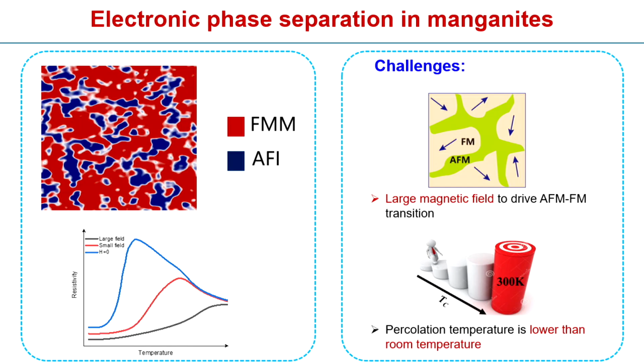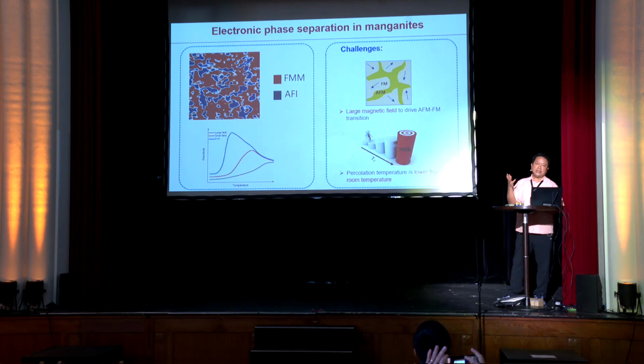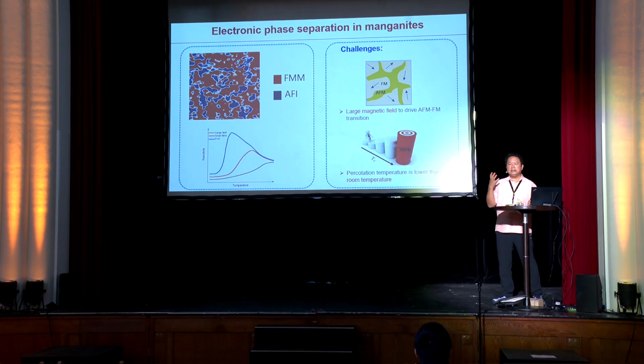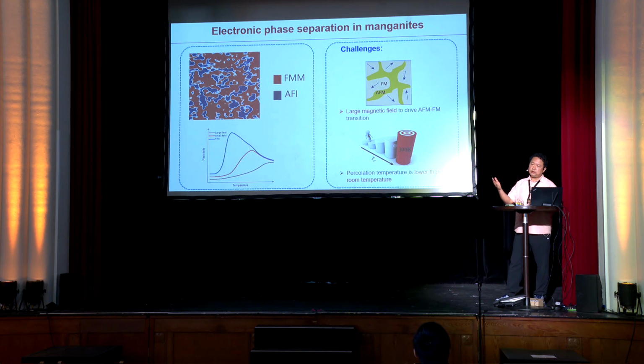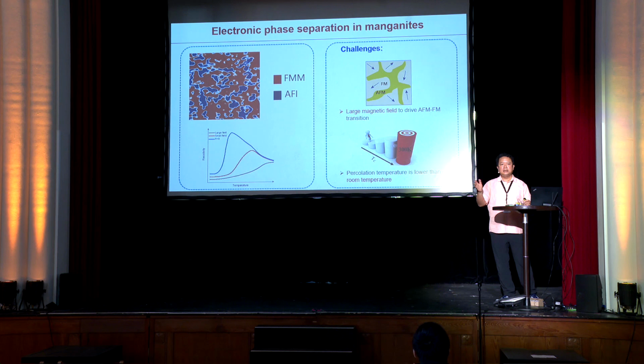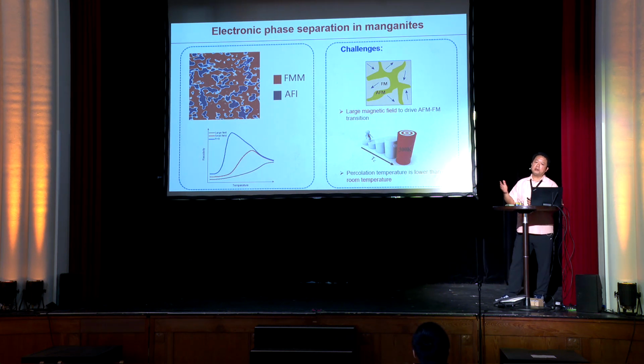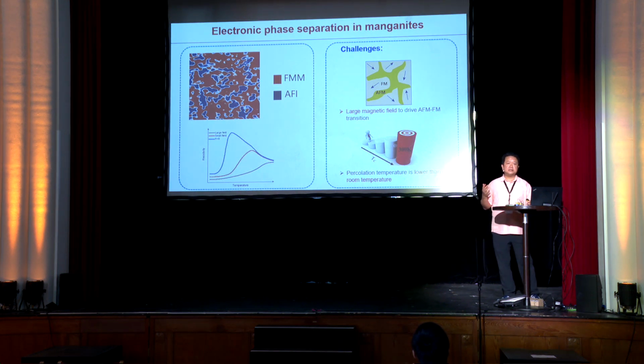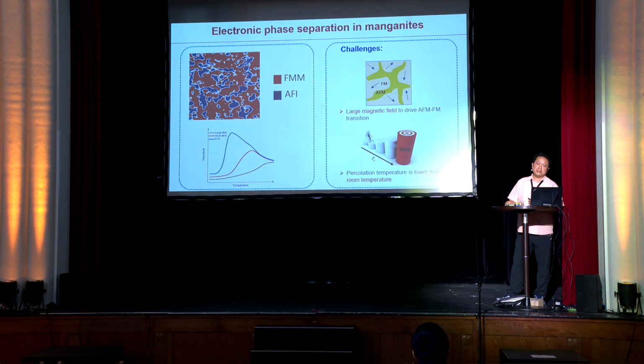The reason that these materials can have such a huge magnetic resistance is the so-called electronic phase separation, meaning that even in a single crystal, in the ground state, there's a coexistence of ferromagnetic metallic and antiferromagnetic insulating phases. When you apply a magnetic field, you can drive a phase transition from antiferromagnetic insulator to ferromagnetic metal, leading to a percolation of the ferromagnetic metallic phase, and then giving rise to a very large change of the resistance. This is the so-called CMR.